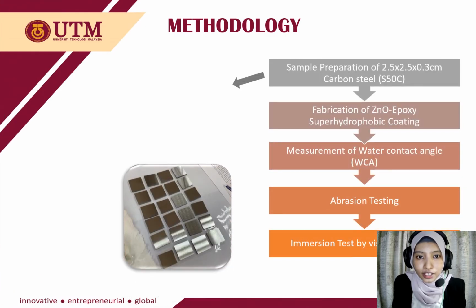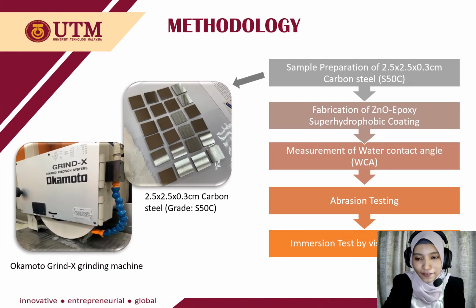As for methodology, we prepared a sample of 2.5 times 2.5 times 0.3 of carbon steel. It was cut and ground using the cutter machine and surface grinder machine, the Okamoto Grind X, available in our precision lab, until it produced a smooth surface like in the photo. It was then cleaned using ethanol solution and rinsed using deionized water, DI water.